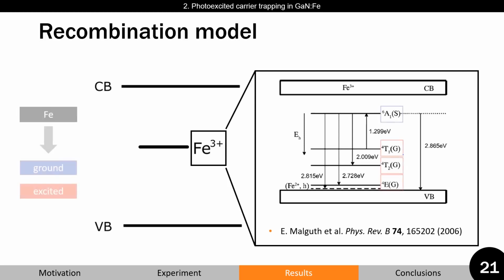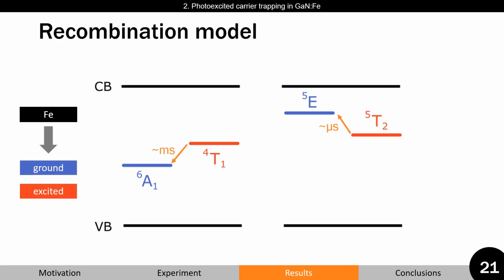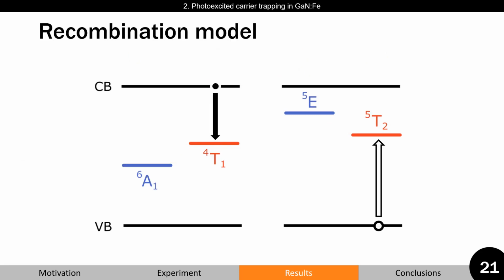Both 3+ and 2+ states can have either ground or excited states. By redrawing our model, including these ground states and excited states, we see that internal relaxation from the excited state into the ground state is in the millisecond to microsecond range. In our experiment, the time between ultrafast laser pulses is only 30 nanoseconds. In other words, there is not enough time for excited states to relax to the ground states. Thus, our evaluated capture coefficient should be attributed to the excited states instead. And it's well known that excited states have much larger capture coefficients than their ground states.